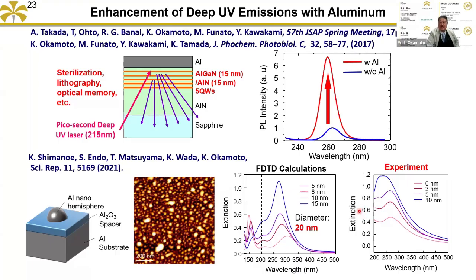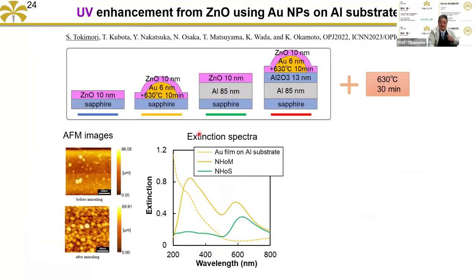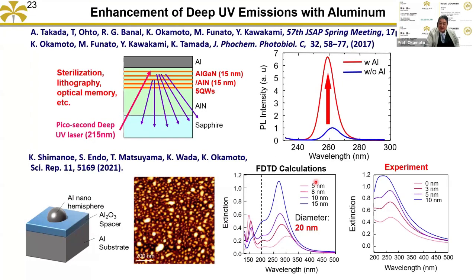Now we found some analysis group that can measure the shorter wavelength resonance. I believe we can show that we can obtain the 150 nanometer resonance peak. That's the shortest record for surface resonance. Okay, then we use this structure to enhance the UV light emitter. But one problem is that aluminum is very difficult to form into a hemisphere structure because the wettability is very high. That's why the structure is not so beautiful.